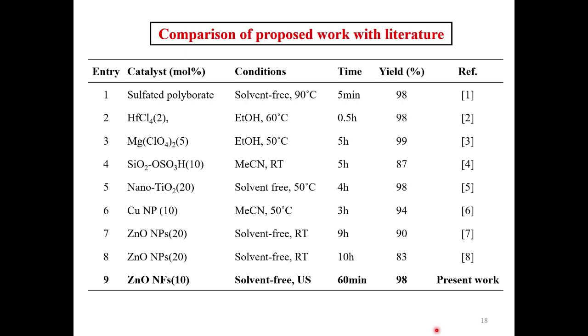If we compare with the others, 90-degree temperature is required, 60 degrees, 50 degrees, room temperature in presence of the solvent. Even with solvent-free nano TiO2, it needs 50 degrees centigrade, and the time required for the reaction is 4 hours. Here 9 hours is required, here 10 hours is required, but the yield is not sufficient. But here only 60 minutes, solvent-free condition under ultrasound cavitation technique.